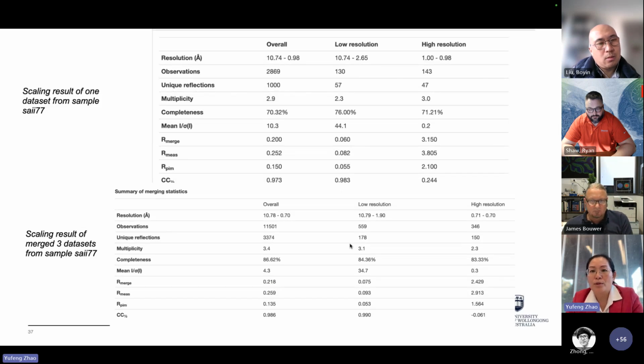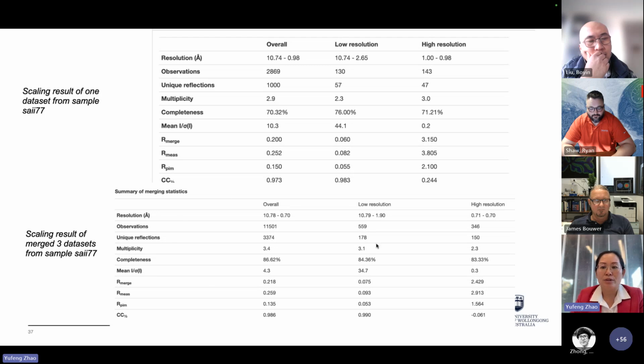For small molecule samples, if you have really good diffraction, we could solve the structure from just one data set. It happened for paracetamol, this kind of easier sample. But in most cases, we collect as much as possible, process the data sets, and choose a few of the best ones to merge together, so we get much better statistical results. So yeah, till now, I think I have gone through the major data processing steps.